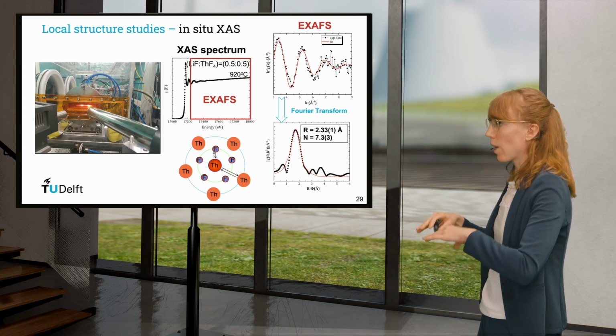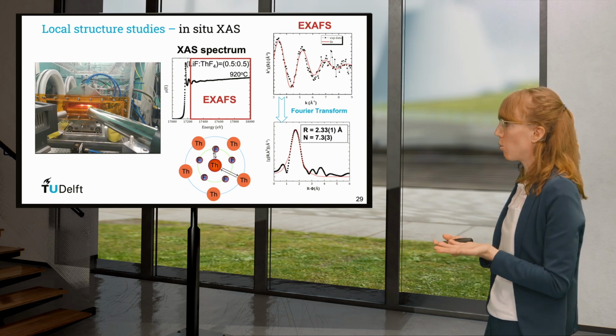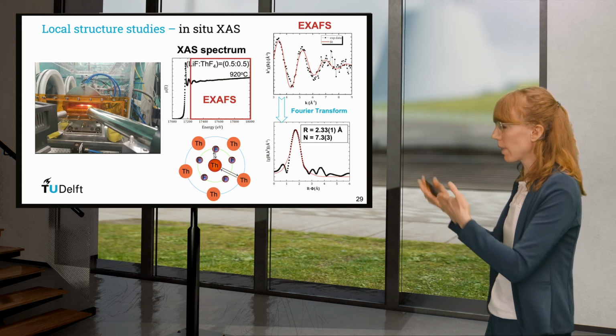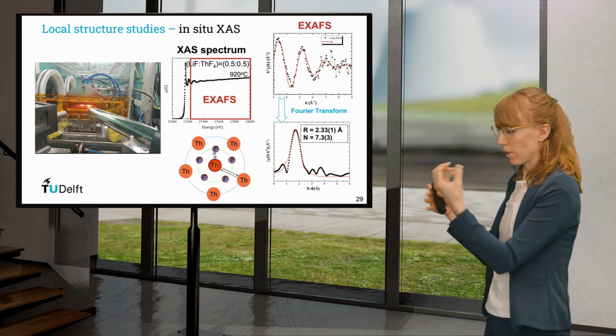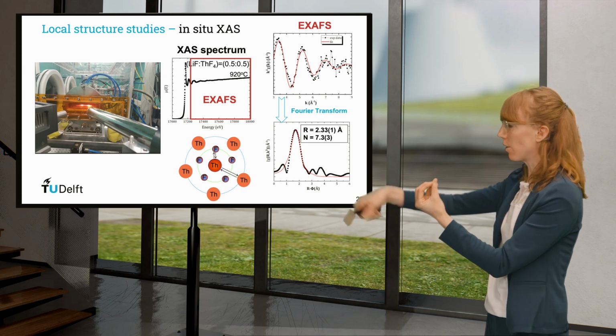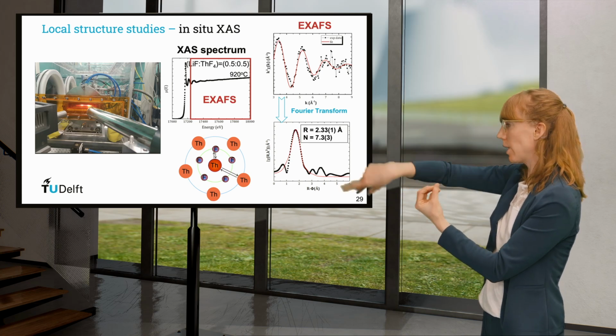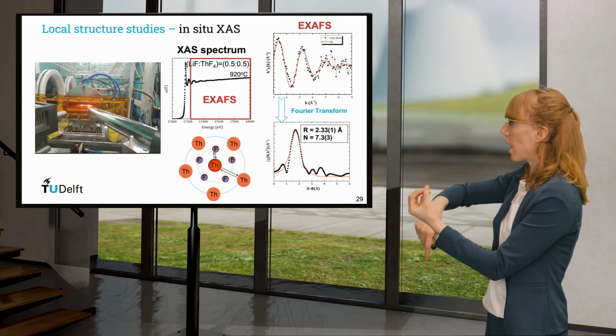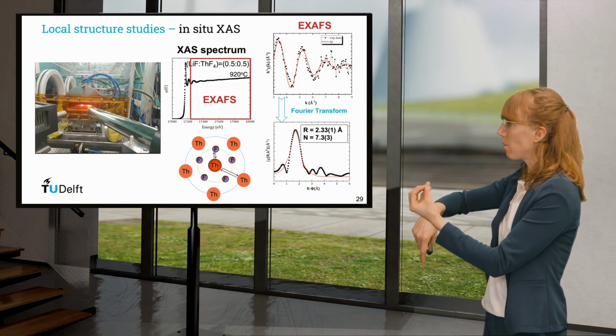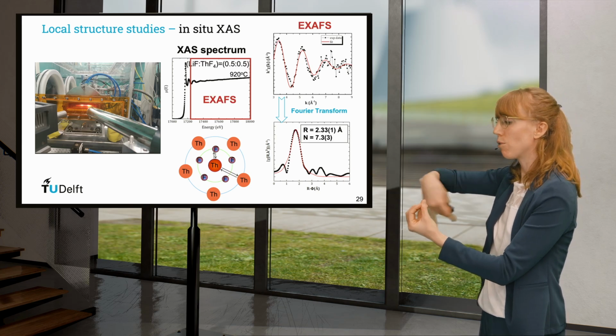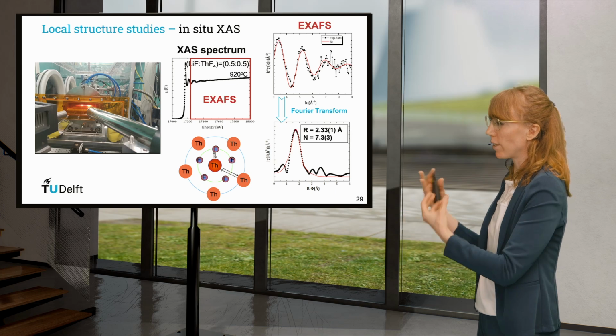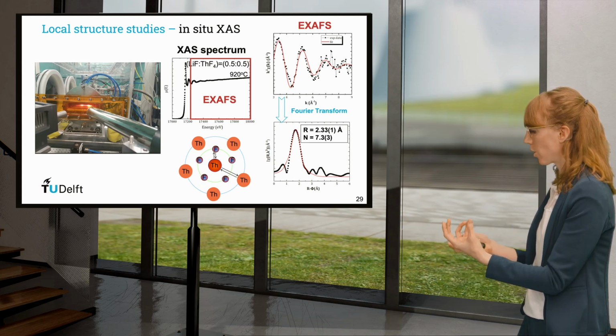We can know how many fluorines there are around a thorium atom. In that case, if you imagine you have a thorium in the center, you have fluorine ions around it at a distance of 2.3 angstrom, and on average you have 7 of these fluorines around the thorium. So that already gives some idea of the local structure.